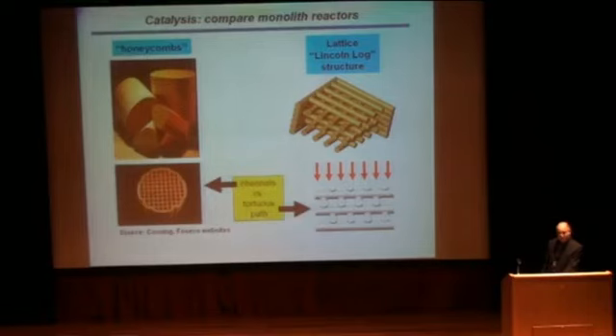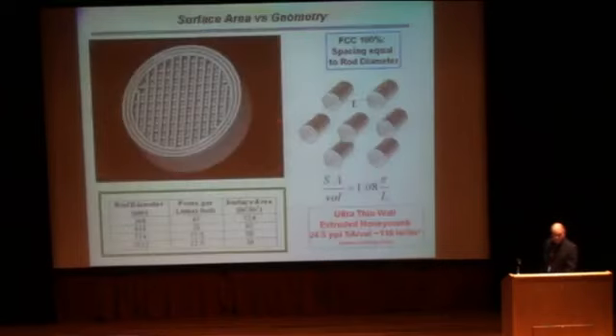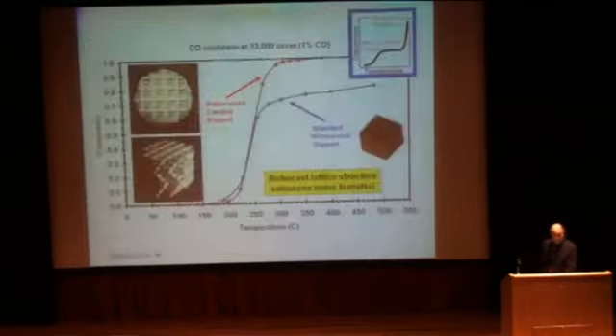So the other thing, though, that these structures could be used for, the exact same structure, is for catalyst supports. Like catalytic converters in the car are made out of honeycombs with straight through channels. In this case, we can make a lattice structure so that the reaction rates can be increased because of the tortuosity that you build into it. And I'll just mention that we can change the surface area by changing the rod size and spacing between the rods to whatever it needs to be.